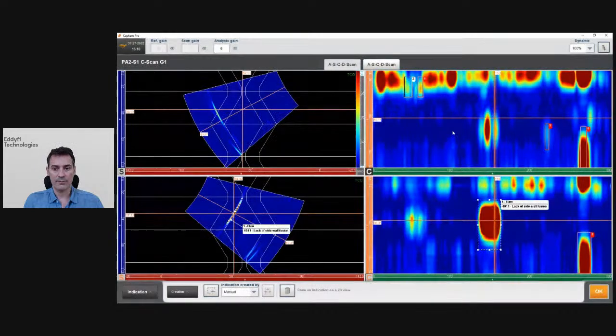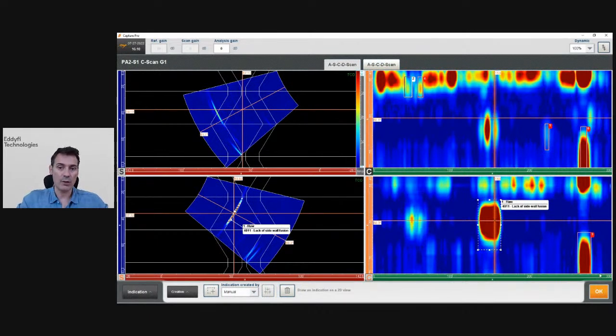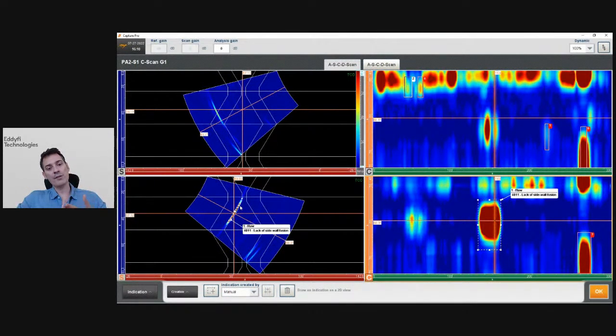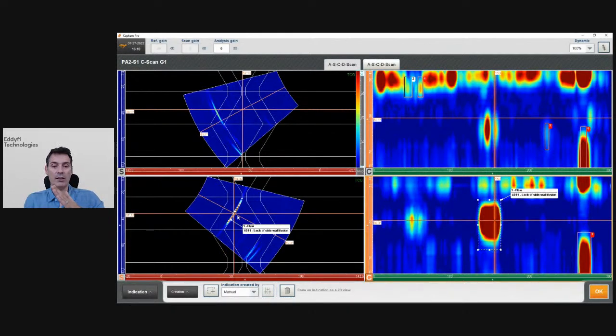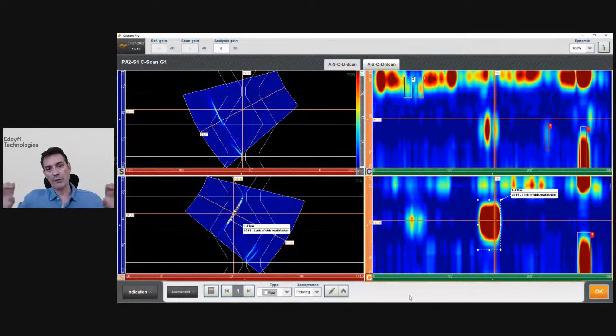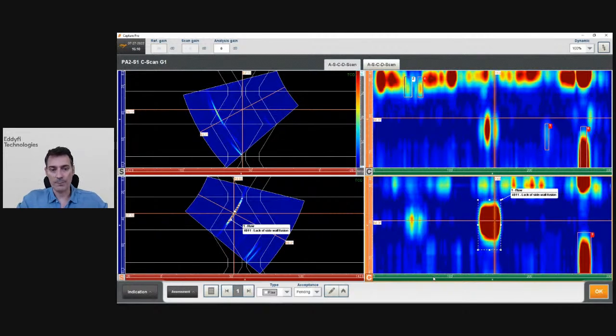That was actually pretty fast — this is a 300-millimeter-long weld, so you can imagine how long it would take based on your weld. Here I have a couple of results. You can see that automatically this indication was detected and classified as a lack of sidewall fusion — pretty good. The software detected this echo, looked at the angle, saw it's close to the chamfer angle, and based on position, orientation, and amplitude, classified it as lack of sidewall fusion. I'm satisfied with the result, so I'll switch to the next one.